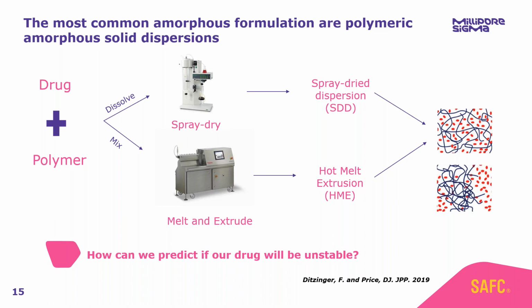So that means within that polymeric matrix, we have areas that have more drug than polymer. And vice versa, we have areas that have polymer-rich domains, so more polymer than drug. So that means that the system is no longer a solid solution, it's no longer homogeneous. And if we have a molecule that is not very comfortable in the amorphous form, you've just provided them with the opportunity to recrystallize, because that's what they really want to do. And so what we can have in those circumstances is a totally phase-separated formulation in which our amorphous API has been able to separate out into drug-rich domains and then recrystallize, forming a crystalline phase within the polymer.